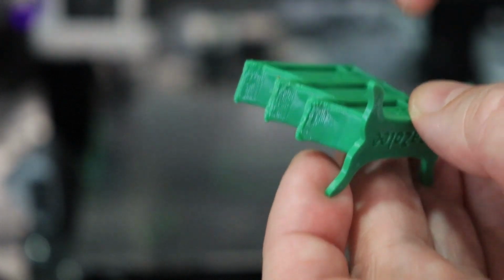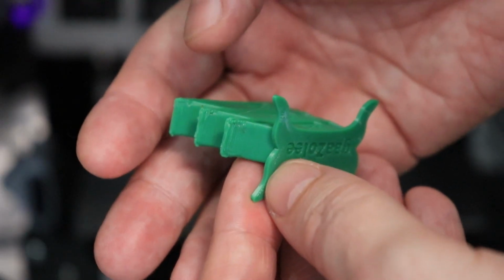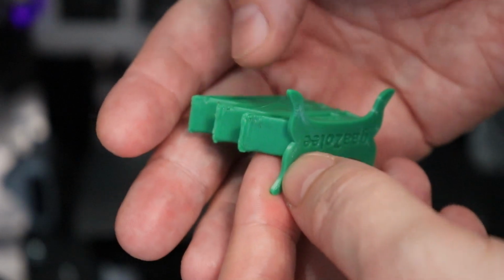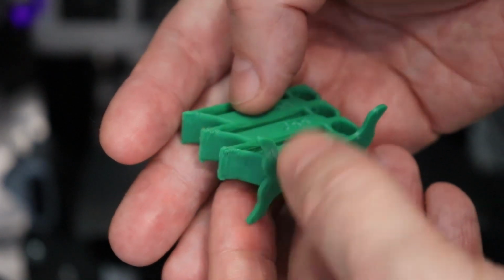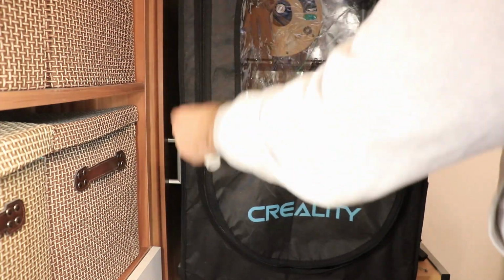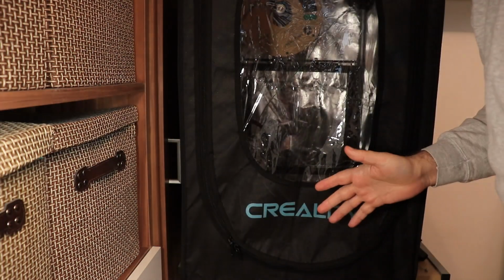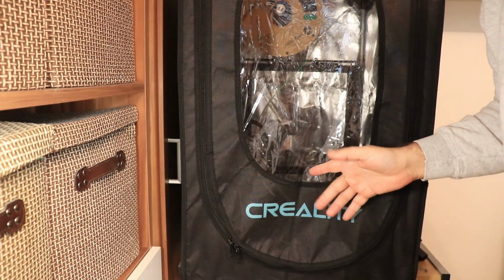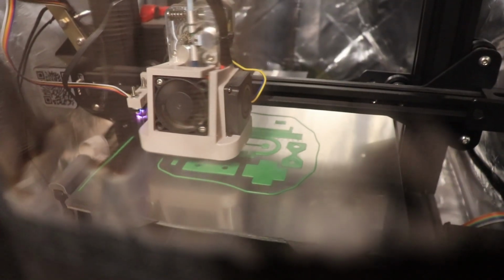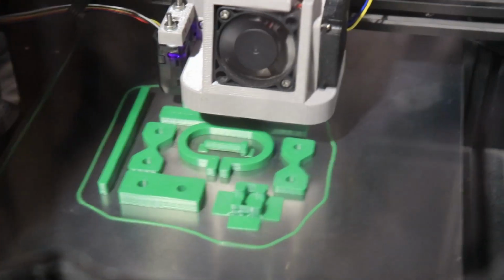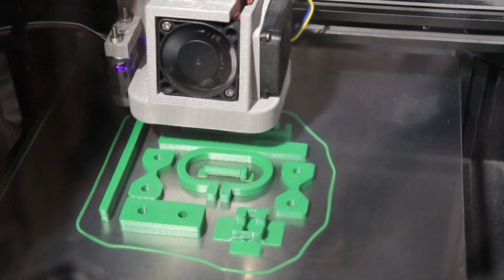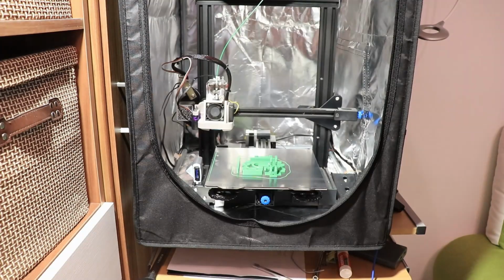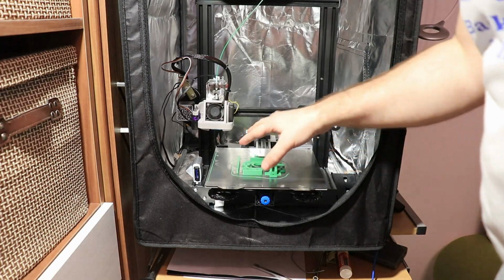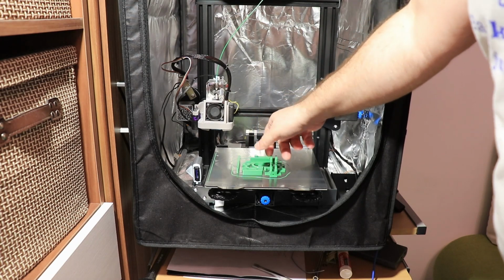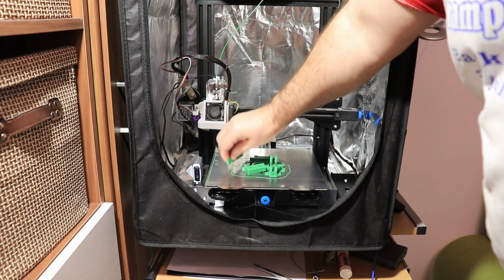But of course I will print out the specimens in the middle, and if everything is okay with the layer adhesion, this ABS might easily become my new favorite ABS filament. And now starting with printing of test specimens at 255 degrees Celsius. The bed already cooled down and I even heard some cracks because it's shrinking, and probably it will be very easy to remove the parts. Yes.